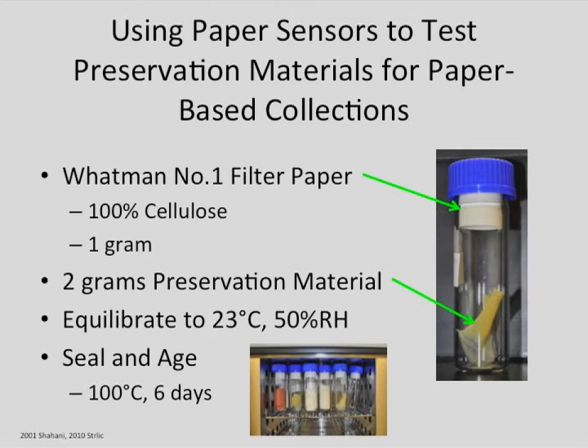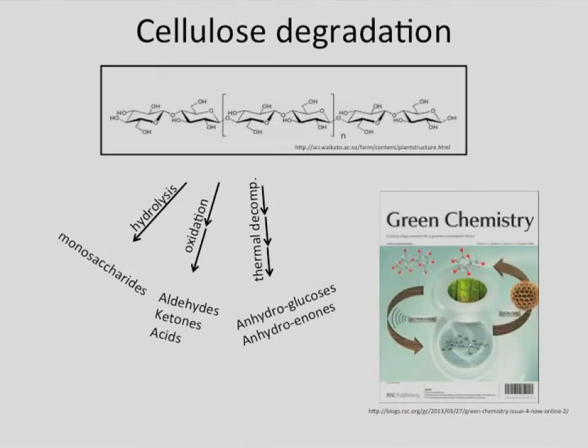They're incubator vials, and they do a pretty good job of holding materials inside. But if you were going to run a test for 2 years, you wouldn't expect the things you started with inside the vial are still there. So this is a much shorter test. Remember, the Oddy test was 28 days. We're at 6 days, but we've bumped up the temperature to 100 degrees Celsius. And what we're looking for is cellulose degradation of that paper.